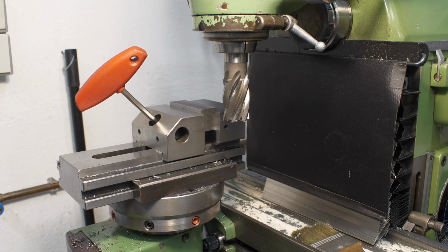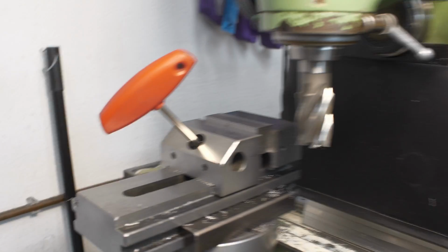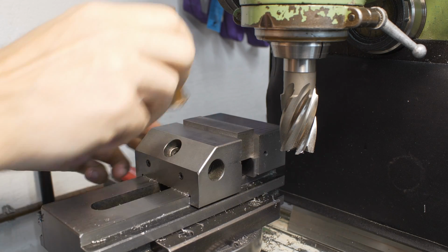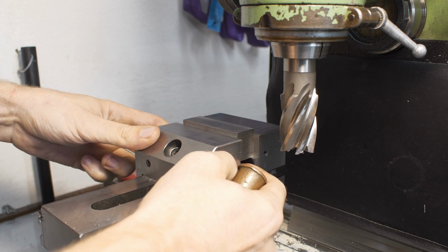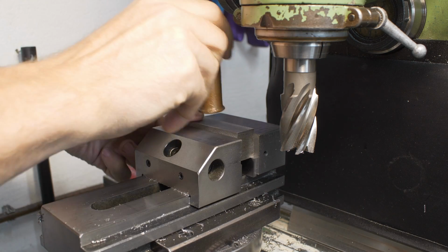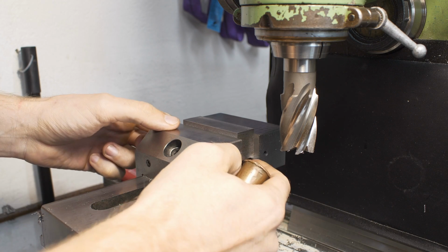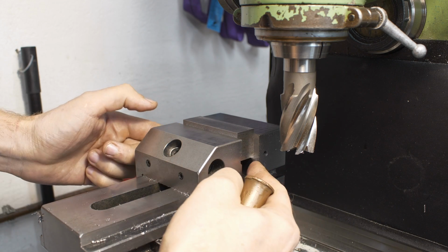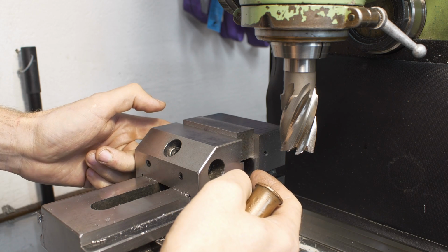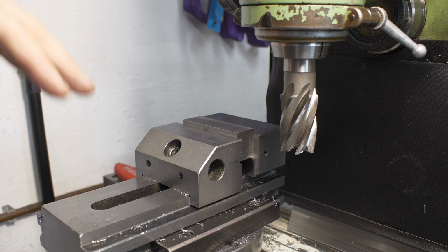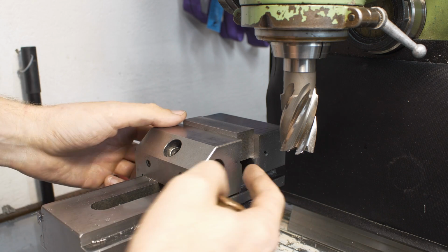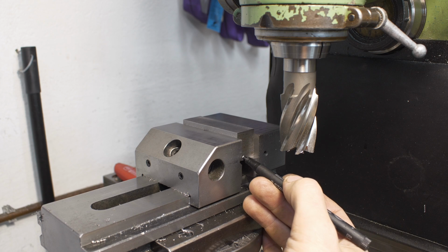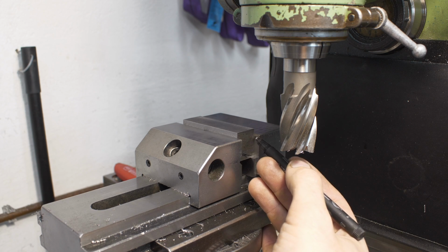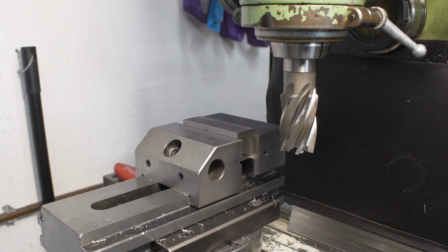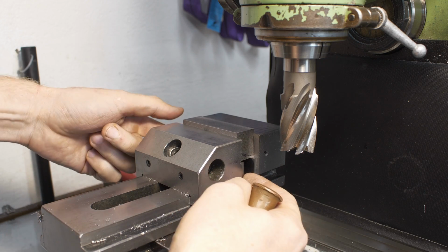Let's get a little bit clear of the end mill. And just by giving it a tap with a copper drift, it seats itself. The rear parallel is super tight and this one can be moved, but it's also tight, means the part is not dead square, which parts rarely are. This means that this lower surface is a little bit tilted like this in relation to this back surface. Not a big deal, probably well within 10 microns because it's still grabbing on the parallel here.